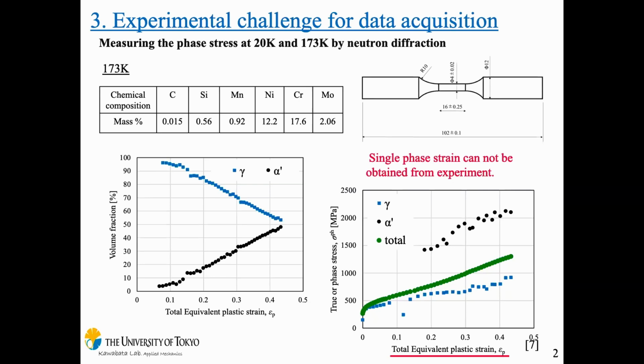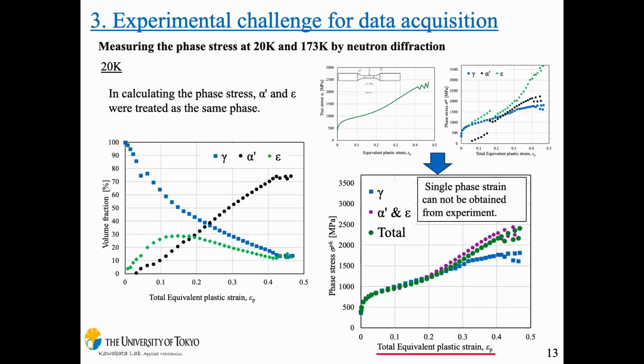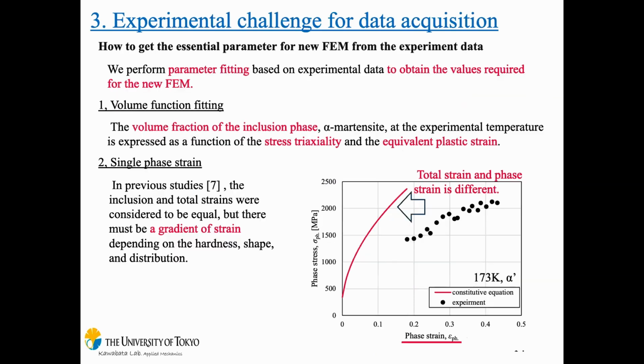It's not single phase ones, so yes. And this is the result at 20 Kelvin. At 20 Kelvin, the epsilon martensite is also detected, but it is difficult to distinguish the alpha martensite and epsilon martensite from the neutron peak, and reducing the number of phases also makes analysis easier. So for the second method, in this study we treated alpha martensite and epsilon martensite as the same inclusion phase.